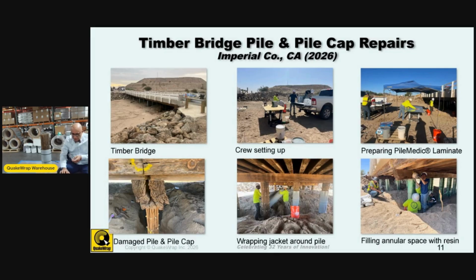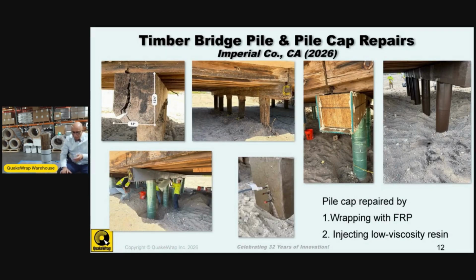When it came to the pile caps, you can use lag bolts to laterally pinch those separations and bring them back together. Then in this case, we wrapped the areas of the pile cap that were accessible all the way around with a layer of resin saturated fabric. The other portions were also formed and wrapped, completely encapsulated in a glass fabric.